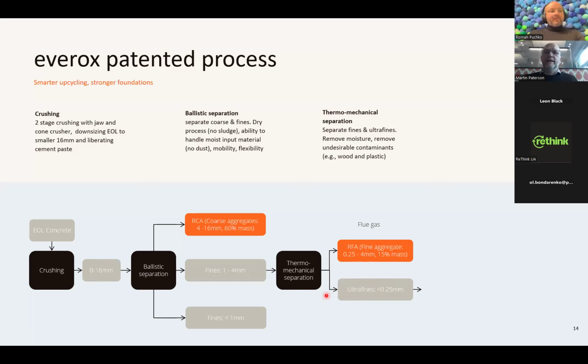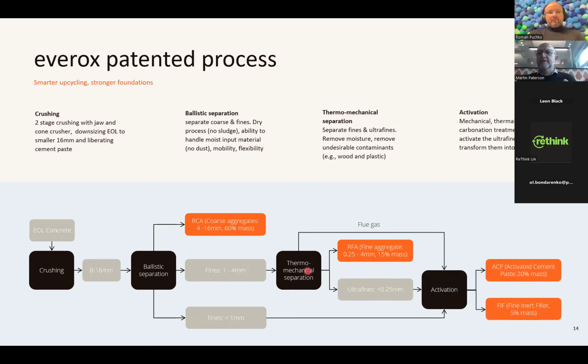But as I said at the beginning, for us, the purpose is, just to remind you, to keep the integrity of the aggregates, take off as much cement paste as possible from them, and then use the fines from the ballistic separator and the ultra fines from the thermomechanical separator to go into the last process step, which is the activation. So we don't only want to use that material as a filler in concrete or in cement. We want to use it as a reactive binder, and thereby we need to activate it.